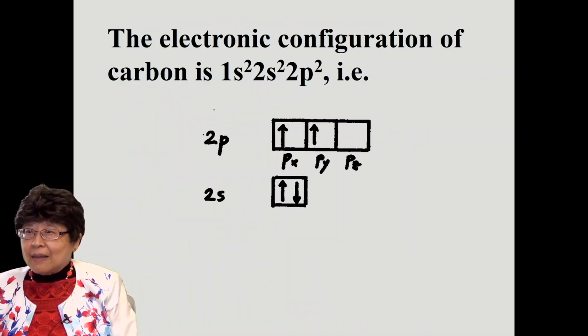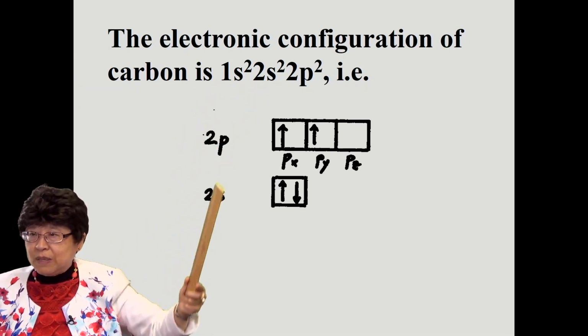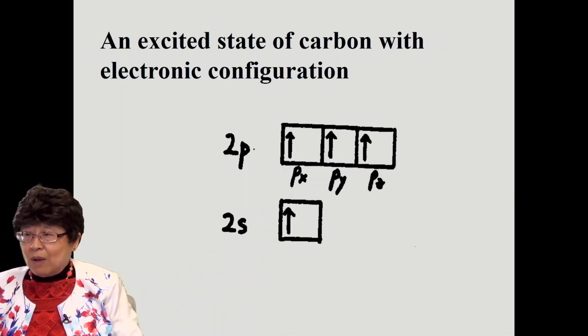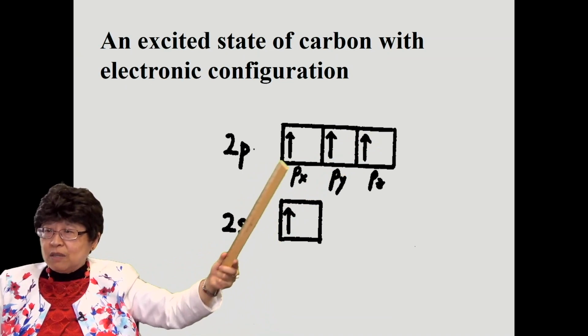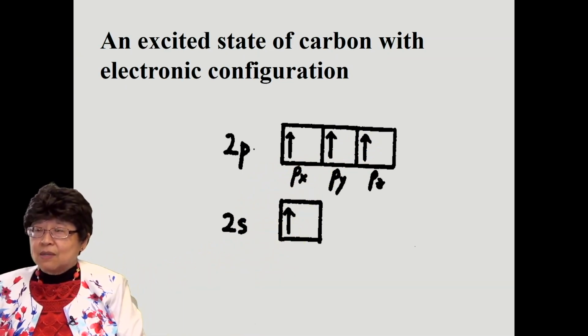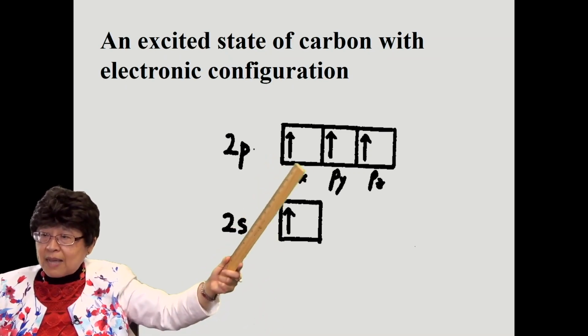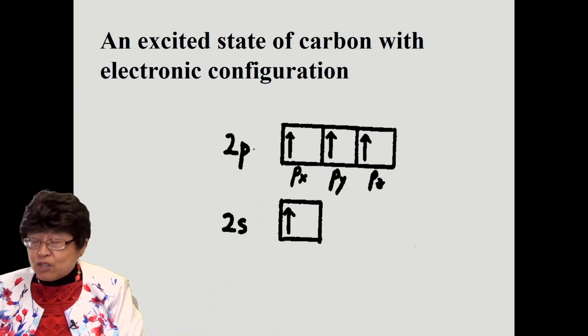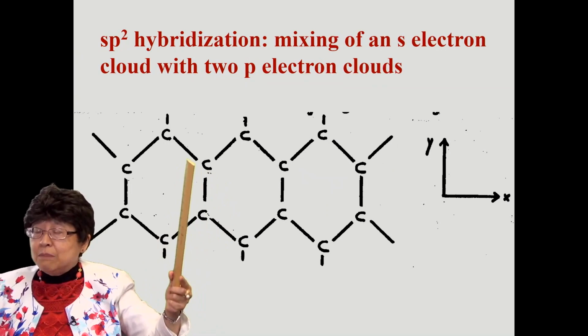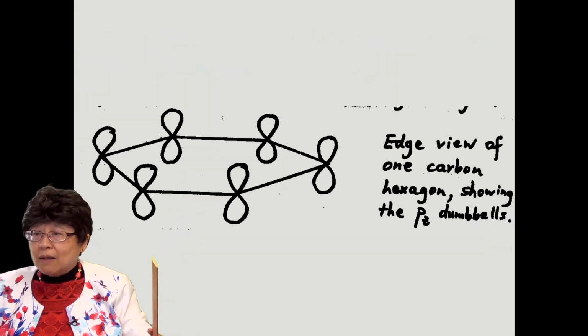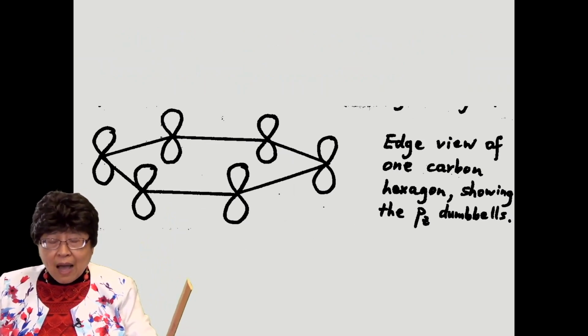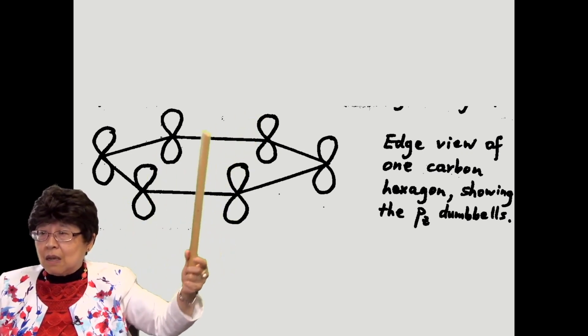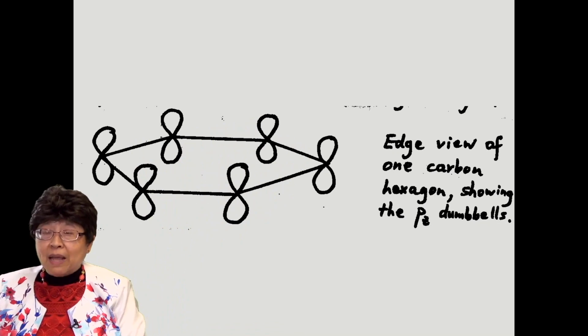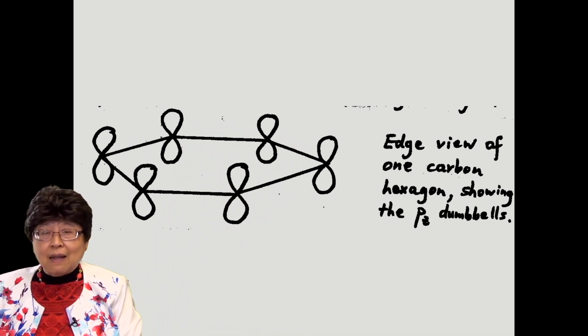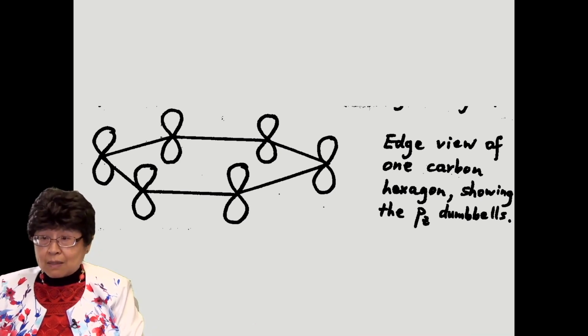Okay? And now the electronic configuration of carbon is 1s2, 2s2, 2p2, like this for the ground state. And one can excite this 2s to the 2pz orbital, and you get 4 unpaired electrons. And you can mix the 2s and the 2px and 2py, what's called sp2 hybridization, and that gives you these in-plane covalent bonds. While the 2pz electron that's left behind from the hybridization would get smeared and give rise to in-plane metallic bonding. And that's why graphite has high thermal conductivity as well as high electrical conductivity in plane, but it's basically an insulator in the out-of-plane direction.